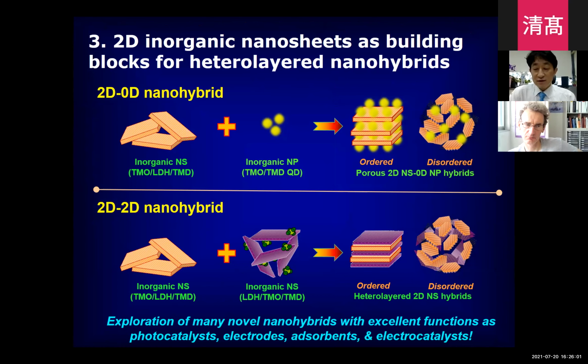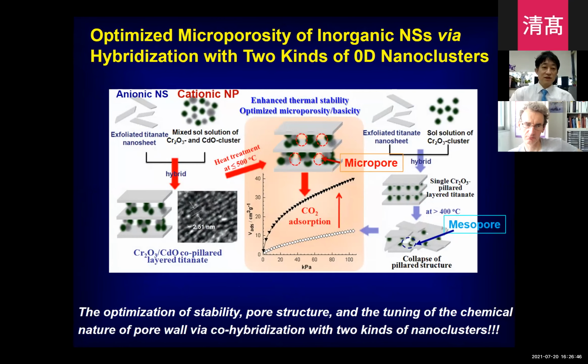Because those materials have a sufficient surface charge, we can use this material as a building block in terms of electrostatic interaction. For instance, we can induce electrostatically induced self-assembly between inorganic nanosheet and 0D inorganic nanoparticles or nanoclusters. So we can get the highly ordered intercalation structure or disordered and highly porous structures. Also, we can restack two different kinds of 2D inorganic nanosheet, and we can get a highly ordered superlattice structure or disordered porous structures. This is the first example of the 2D-0D system.